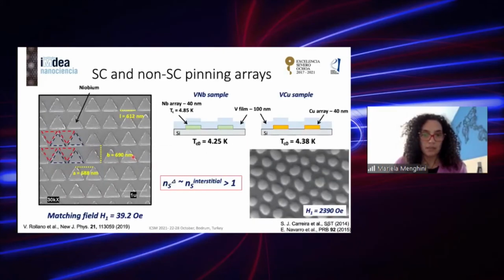So in practice, this is what we have done. It is basically an array of, in this case, niobium triangles, with a lateral dimension of the order of 600 nanometers. And then on top of that, we deposited a vanadium film of 100 nanometers.